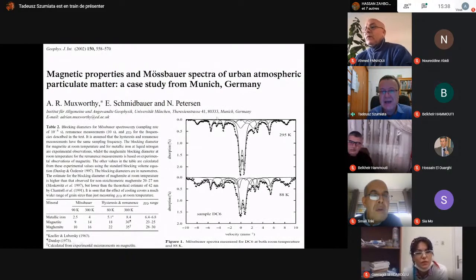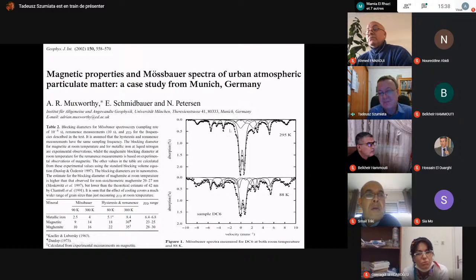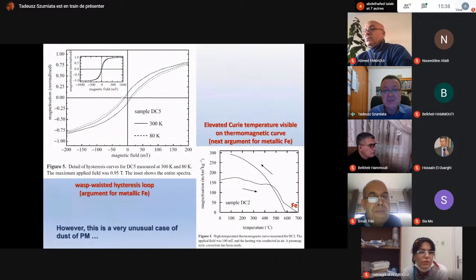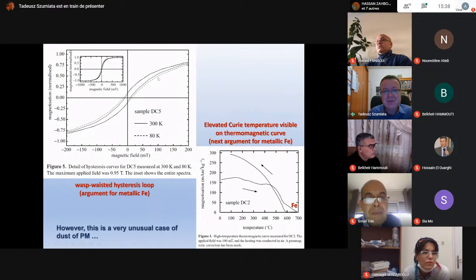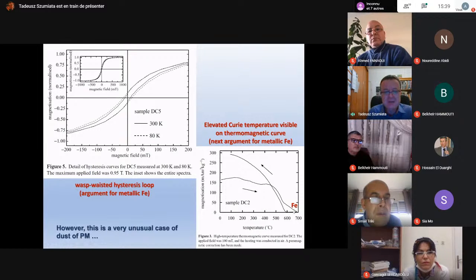But why they have so many metallic iron here? Probably the place of collection was very close to the railway junction in Munich, in Germany, and probably they have continuous source of metallic iron, of course, because of some kind of friction when the trains were traveling through the rails. And of course, in this case, they could see this special wasp-waisted feature in magnetic hysteresis loops, so they are happy. And also they see the shift of Curie temperature towards higher temperatures. So they really could see beautiful iron, but it is an exception, something unusual. Normally we can expect no iron or very defected iron, as I showed.